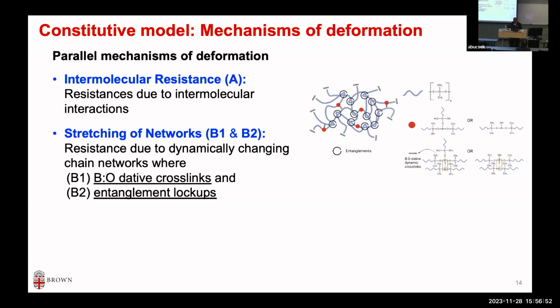So given the information, we found these 2 mechanisms. For polymers, if you look at any viscoelastic materials, typically you have 2 different mechanisms going on. One is intermolecular resistance. So what happens in the nearby molecules? They may have some elastic behavior, and as your sliding chains pass each other, you also have some kind of dissipative or friction-like mechanism. That is captured in our model in mechanism A. And then same thing about the fishnet, you're stretching the whole fishnet, right? Network stretching, that is known as the rubber. That is modeled in network B, the second network. The second network has two components, B1 and B2, because you have two different dynamic reversible crosslinks: boron oxygen, the coordinate bond, and the entanglement-based. So that's the framework of our model.